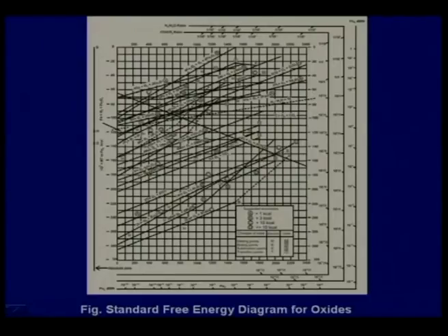It is not 1 V2O5. The idea is, if we write always a reaction in terms of 1 O2, then we can add these figures to find what will happen when a more reactive metal replaces another. The more reactive metal replaces a less reactive metal from its oxide.